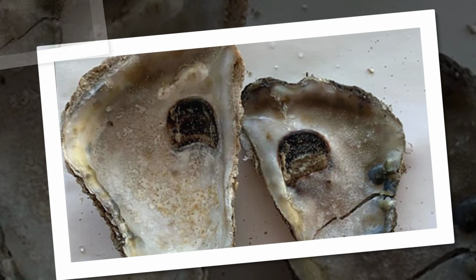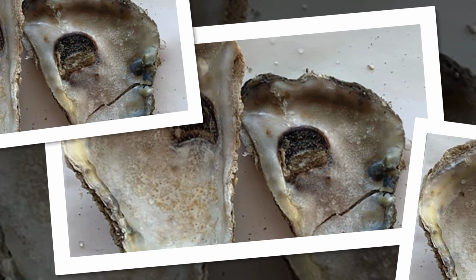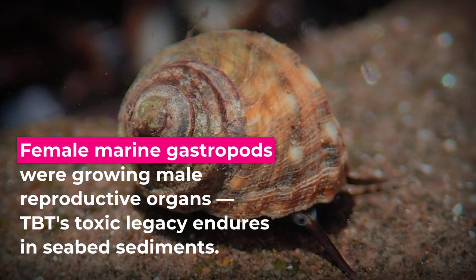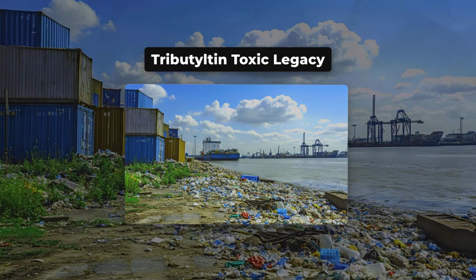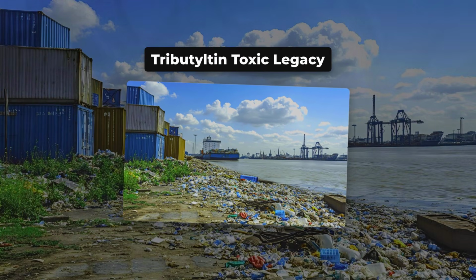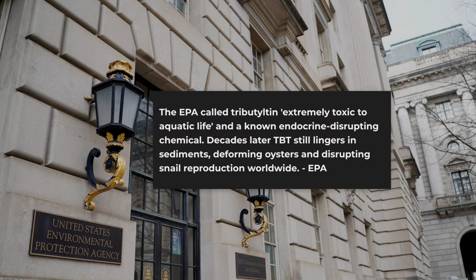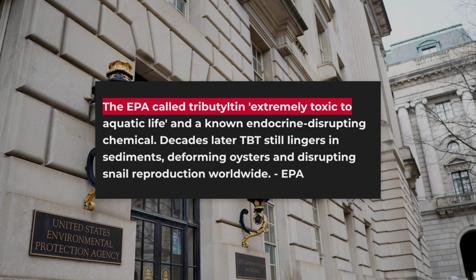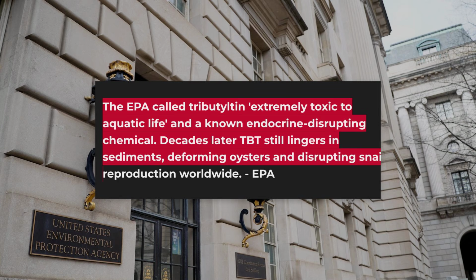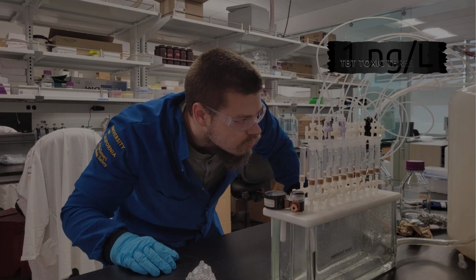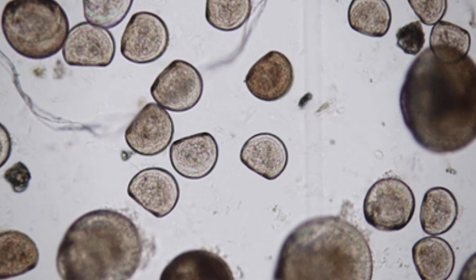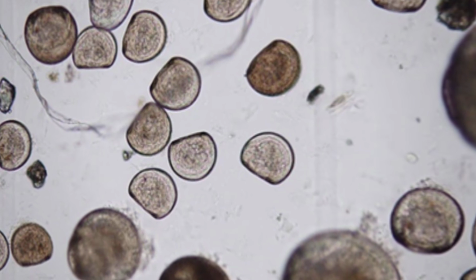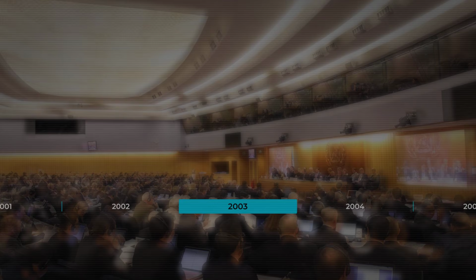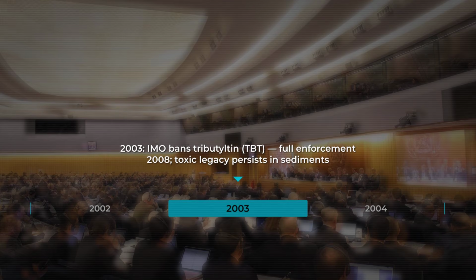Oyster populations near busy ports were developing grotesque shell deformities. Female marine gastropods were growing male reproductive organs. Entire coastal ecosystems within harbor zones were being chemically disrupted. The EPA described TBT as extremely toxic to aquatic life and a known endocrine disrupting chemical. At concentrations as low as 1 nanogram per liter, 1 billionth of a gram per liter, it was causing irreversible reproductive damage in shellfish. The IMO banned TBT in 2003 with full enforcement by 2008.